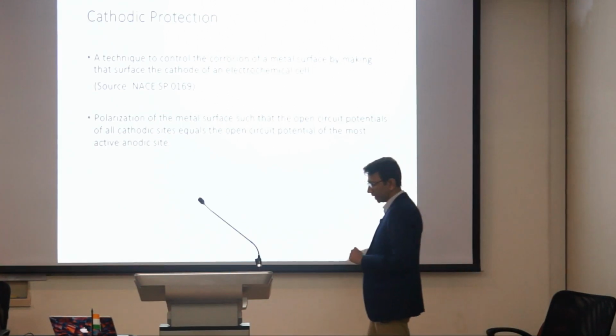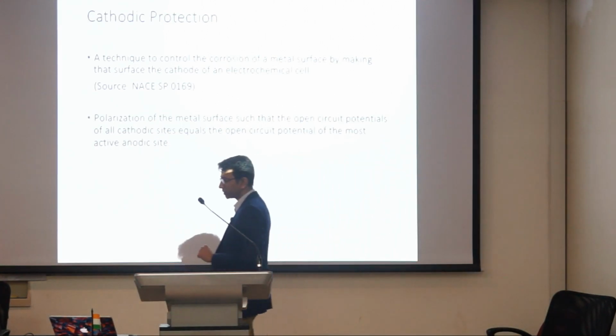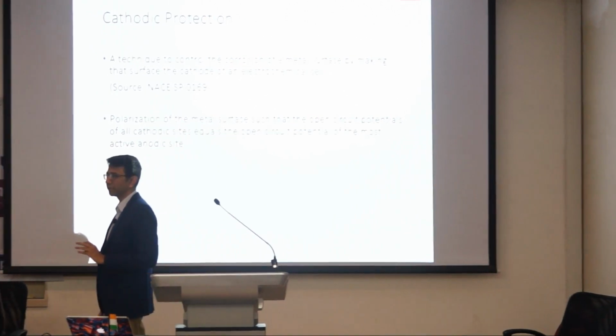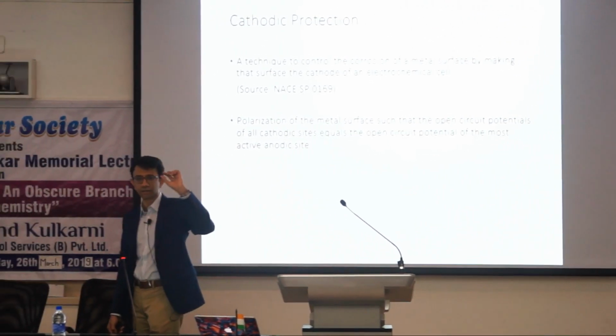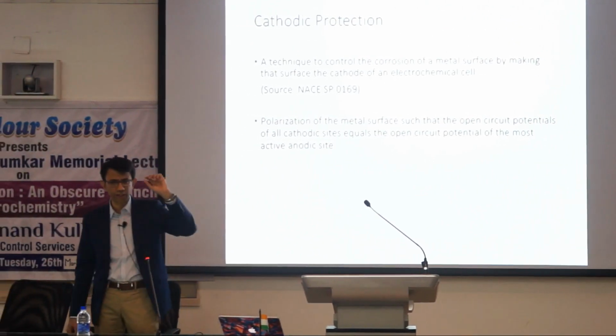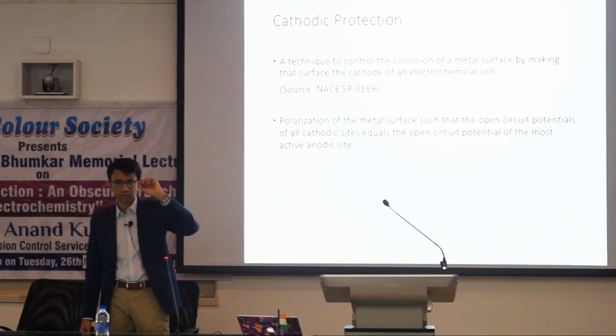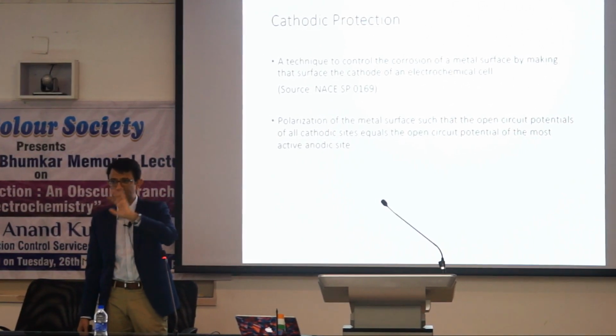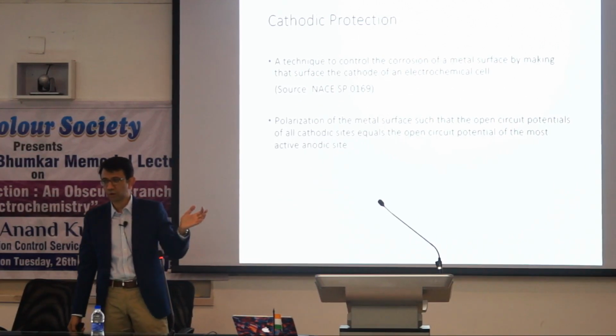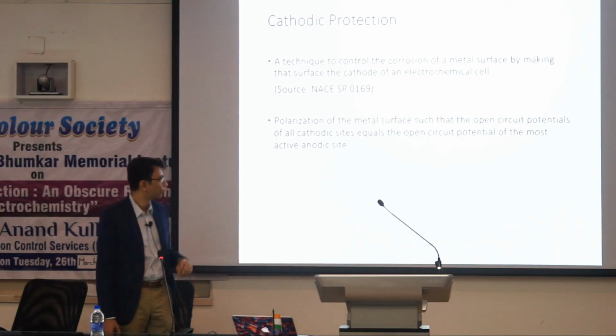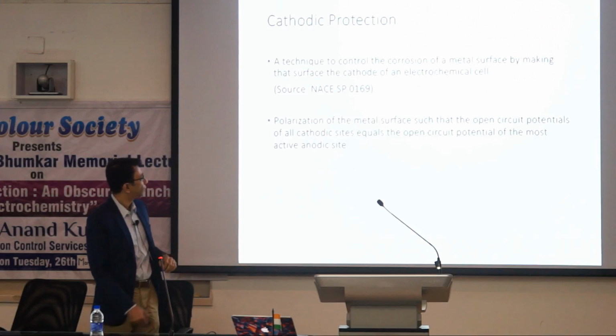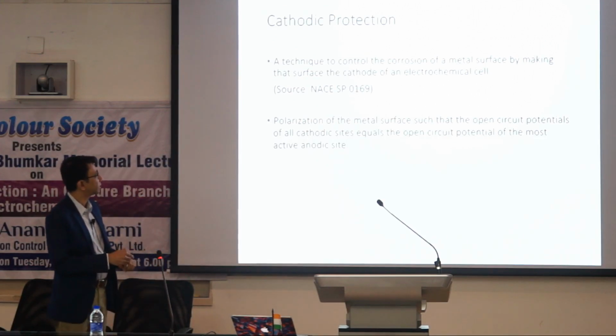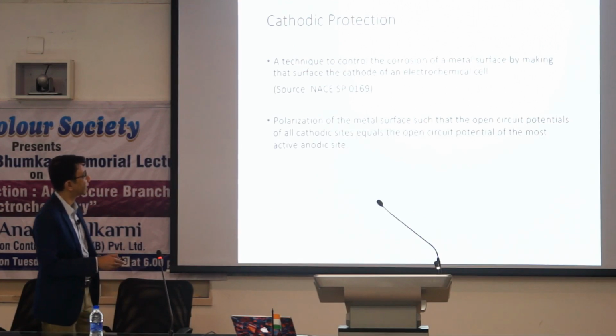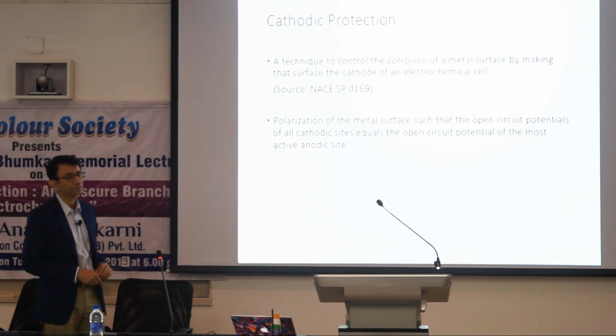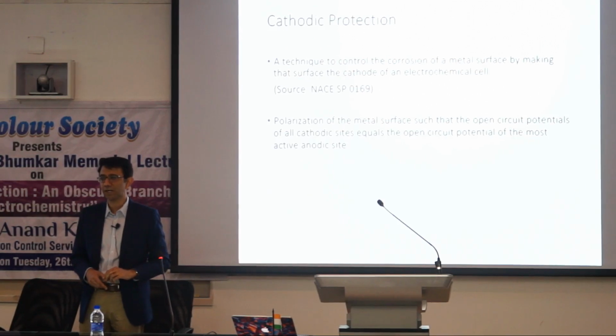So when Humphrey Davy actually looked at protecting the copper-clad ships, he realized that zinc ingots, and if you had sufficient number of zinc ingots which were placed on the copper cladding, it was able to protect the copper of the warships. And so this is the genesis of the definition of cathodic protection, a technique to control the corrosion of a metal surface by making the surface the cathode of an electrochemical cell.